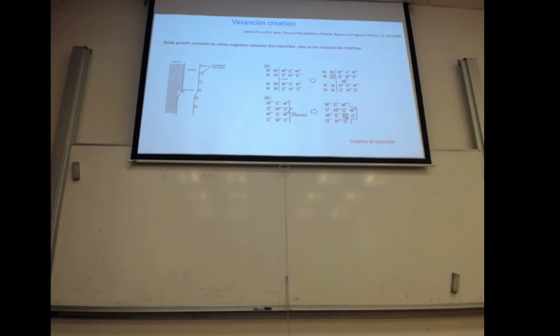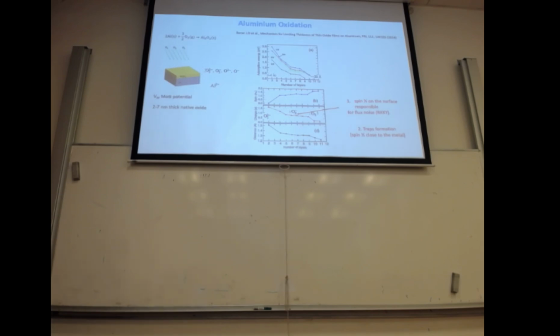What is crucial in this theory is how this migration happens. Basically, this migration happens because, as I told you, you have these negatively charged adsorbed oxygen molecules that come close by, and then from this metal, the cation gets out, and when they get out, basically they create vacancies. And so this is how the oxide grows, and it grows leaving these vacancies. And then I will show that these vacancies actually are really crucial for the formation of this two-level system.